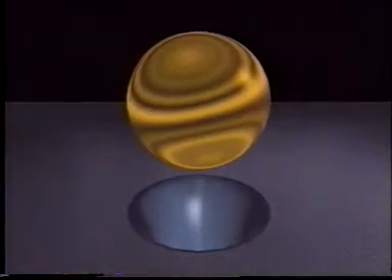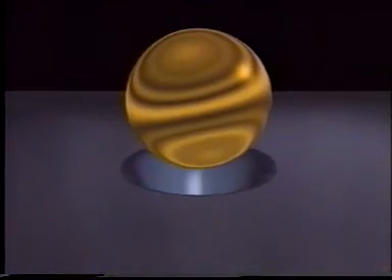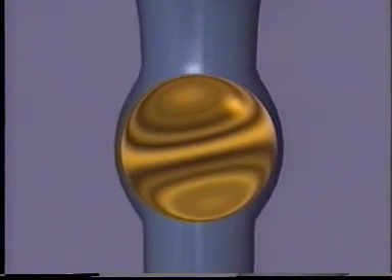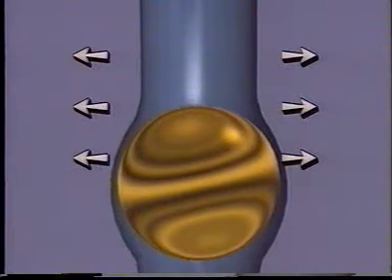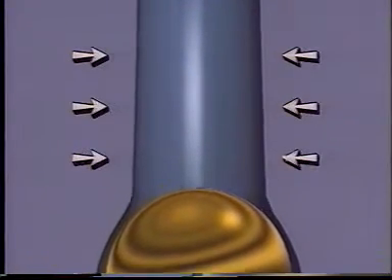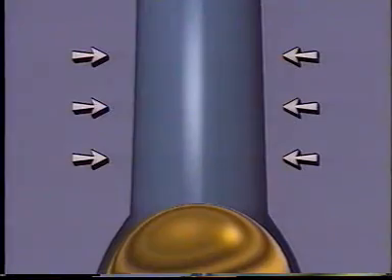Critical holes, such as oil holes in highly stressed parts, can be strengthened by ballizing. This process involves pressing a hardened ball through a greased hole that is slightly smaller than the ball. The ball stretches the wall of the hole, which then contracts after the ball has passed through. Thus, compressive residual stresses are developed in the hole. This is the positive side of mechanical pre-stressing.